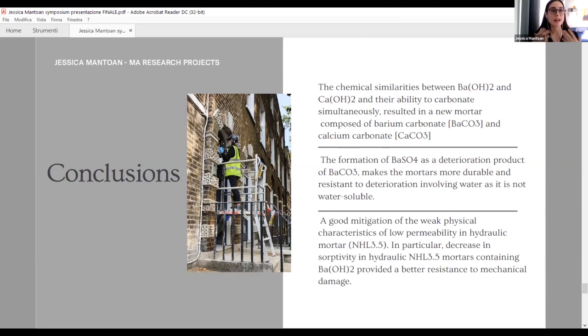Another positive result that I was able to achieve through this research is that, in particular for hydraulic mortar, the use of barium hydroxide helped to mitigate those characteristics that are usually considered negative about this type of material. In particular, the low porosity and permeability are slightly mitigated through the use of barium hydroxide, making that type of mortar more resistant not just to salt and acid rain, but also more generally to any type of mechanical damage.